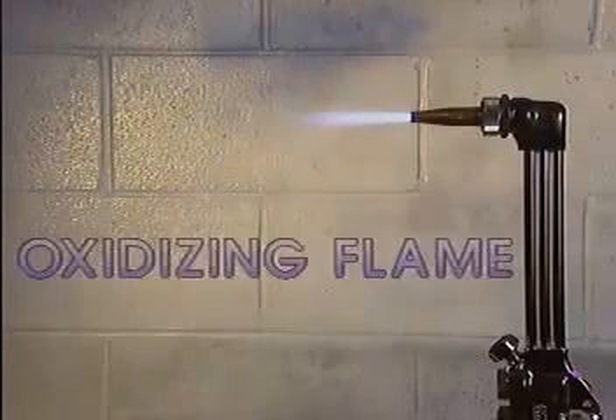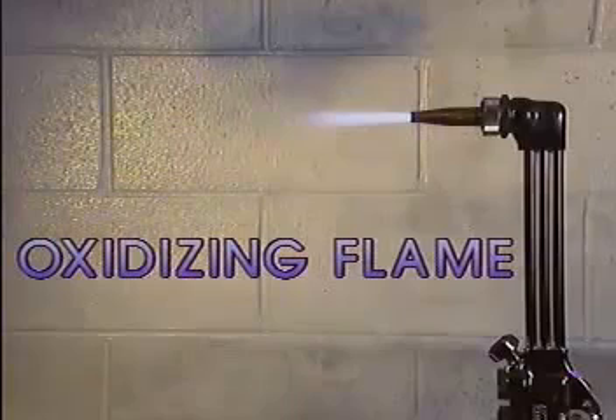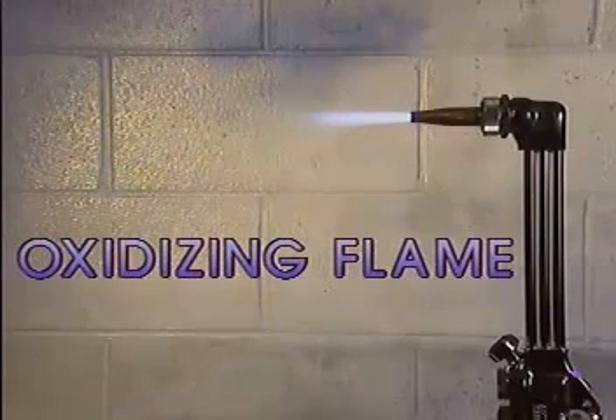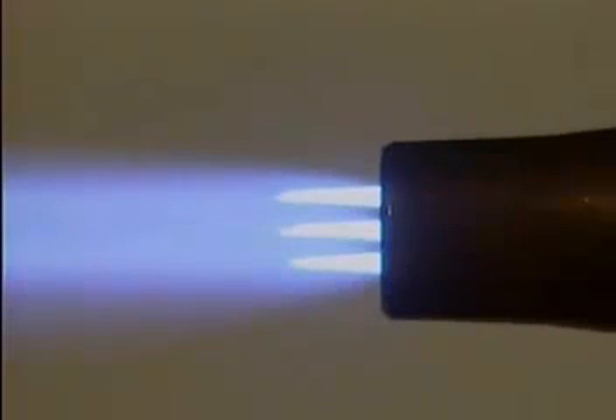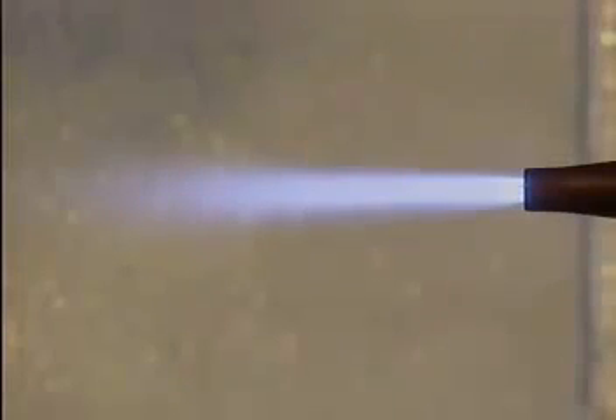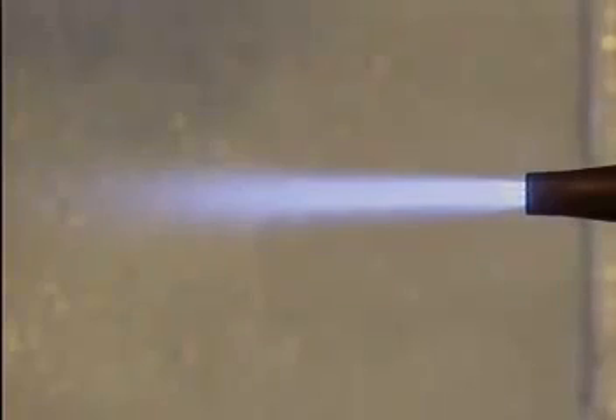The third flame type is an oxidizing flame. An oxidizing flame has an excess of oxygen. Its inner cone is shorter, bluer in color, and more pointed than the inner cone of a neutral flame. Its short outer flame envelope often fans out at the ends. An oxidizing flame is the hottest of all gas flames. However, an excess in oxygen is detrimental to welding operations. Excess oxygen can combine with the base metal to form metal oxides, which will weaken and deteriorate the joint.